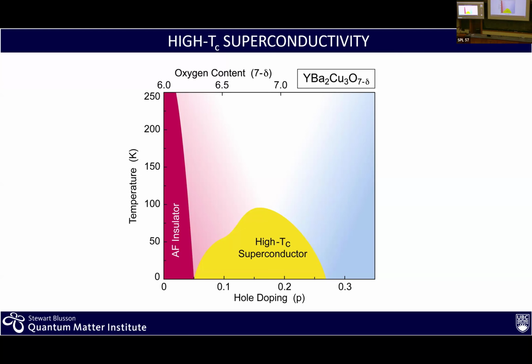And here you find a superconducting dome with temperature approaching 100 Kelvin. Now, what is surprising is that at low doping level, you don't find a metal, which usually would be what you expect as an adjacent phase, but you actually find an insulator, and it is actually magnetic, with an antiferromagnetic order for the spin in the copper-oxygen plane. So just the existence of that phase was a big surprise. So the next step was then to understand what is the electronic structure underlying this phase diagram, and which then eventually is the one from which superconductivity emerges.